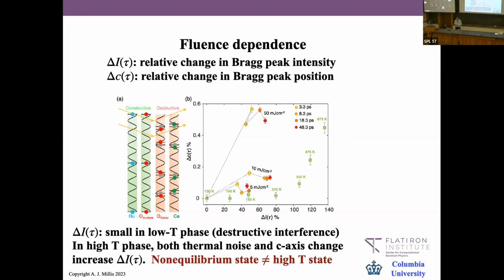All right, so here's the argument that it's not. This is a slightly complicated plot, but the basic statement is that in particular for this 008 peak, there's an almost perfect—not complete, because you can still see the peak—but almost perfect destructive interference. So the amplitude of this peak is intrinsically low compared to other peaks.